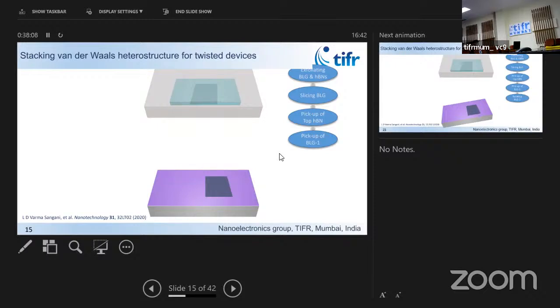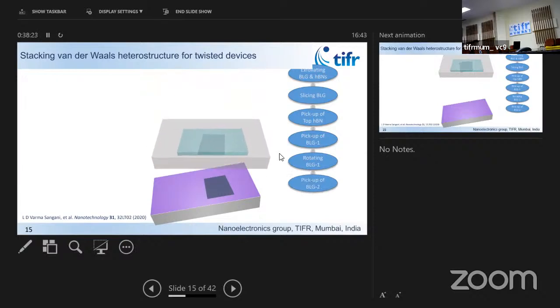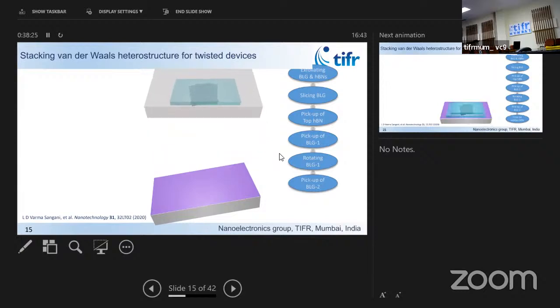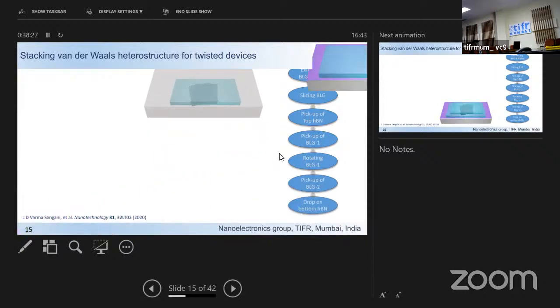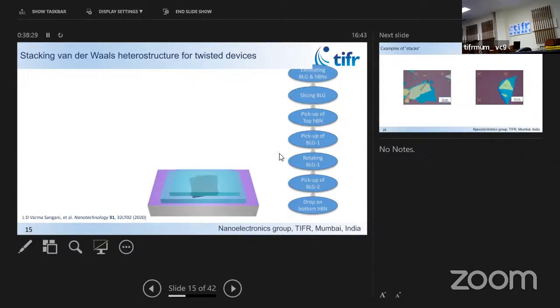Now what you do is rotate the bottom remaining piece to a precise angle, what you want, using a mechanical rotator, so you know what the angle is. Then you have a precise relationship between the twist angle of these two materials, and when you bring them together, you can make a sandwich, or what we call colloquially a stack. It's a stack of 2-dimensional materials. And then one can make devices out of it.